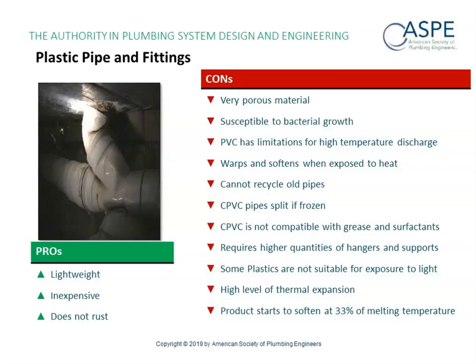We talked about the continual use temperature of PVC being 140 degrees, and when you're in kitchens, breweries, food processing plants, you will find higher temperatures going down the drain, and the plastics will actually start to soften at 33% of its melting temperature. What you're seeing here in this picture is from a brewery in the Midwest. That's underneath the flooring, obviously, but this particular brewery has never seen anything over 180 degrees go down their drain. They measure everything going through, and they've never seen anything more than 180 degrees.